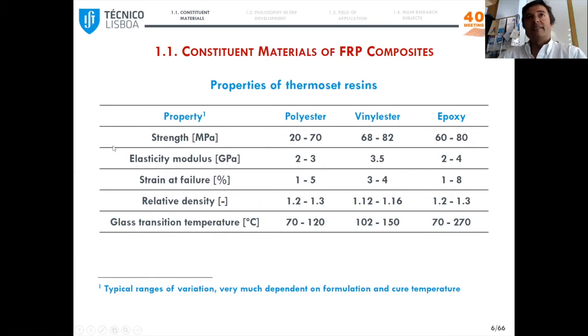Now let's look at the thermoset resins that are more often used with FRPs. You can see that their mechanical properties are relatively similar, being 1 to 2 orders of magnitude lower than those of the fibers. The most relevant difference between these resins is basically their ability to bond the fibers and their durability, which is maximum in epoxy and minimum with polyester.